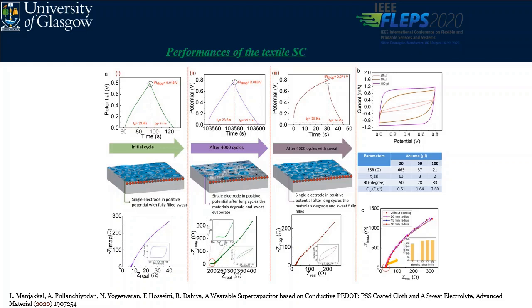So this means that such evaporation occurs during long cycling. There is an evaporation of sweat, but the major advantage is that we can easily refill the sweat into the textile, and then the device will work again. But some of the drawback in the working performance is due to material degradation.